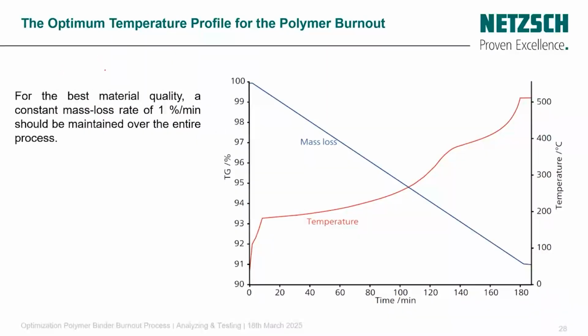Then we can do the optimization of the profile. So in this case, the optimal temperature profile for the polymer binder, you can see by the mass loss. And for this case, the best material quality at a constant mass loss rate of 1%. Also here, I can show you in the demo live how we can adjust it. You can make it also 0.5, or you can customize as you want. It's up to you. And in this case, we can achieve the optimum temperature profile by controlling the conversion rate.